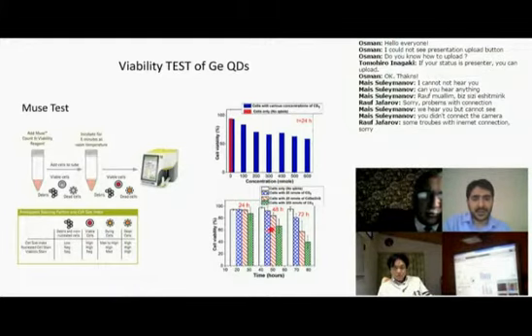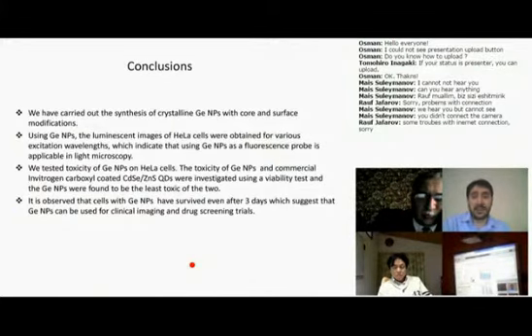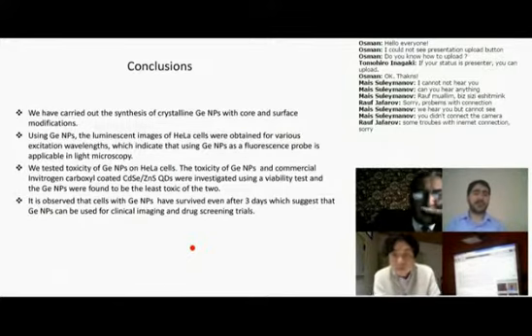On the second day, after 48 hours, when we compare our particles with the commercial one, it's very nice actually. They are not killing cells. On the third day, as you can see, even the 10 times more concentrated particles are not killing the cells that much. They are not that toxic.